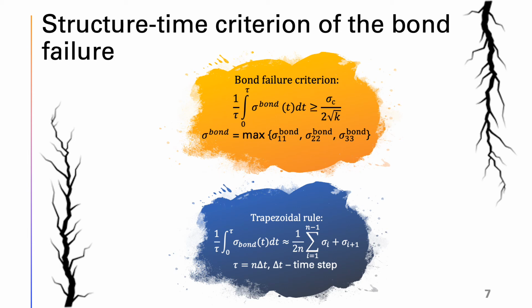In order to calculate an average bond stress value over the incubation time tau, a stress time history of each element is stored over the previous n time steps. Calculation time step is selected so that it's a multiple of the incubation time. Then, using a trapezoidal rule, time histories of the bond stresses on each area are integrated and a maximum positive value over all areas is compared with the critical value.